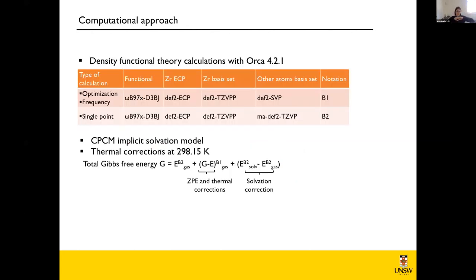So these are some very quick computational details, but essentially we're just doing DFT calculations within ORCA. All the details are provided here, but to have results that are somehow comparable to experiments, we run frequency calculations, not only to ensure that we have a minimum structure, but also to have some thermal corrections for the room temperature binding energies. And we also attempt to account for the presence of water in the MOF by using implicit solvation.